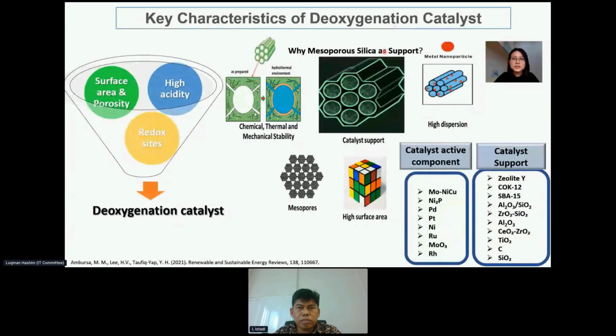Thus, mesoporous silica was selected for the deoxygenation process, due to its advanced properties such as chemical, thermal, and mechanical stability. It shows high surface area, and it has a suitable pore size, which is mesopores, able to fit lignin-based compounds, and it has high dispersion for the active metal. Other than the mesopore support, active components such as transition metals as well as rare earth metals are very suitable to improve the overall catalyst, because they can help to improve the acidity as well as the redox sites, providing a synergistic effect between the catalyst support and the active sites of the metal.